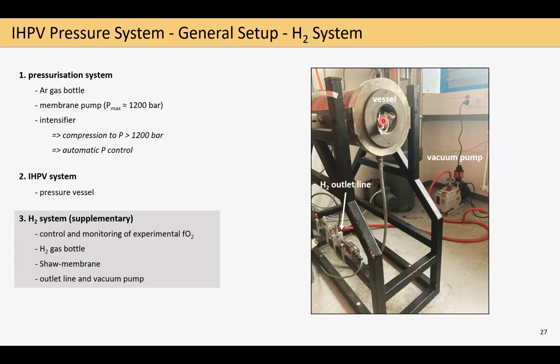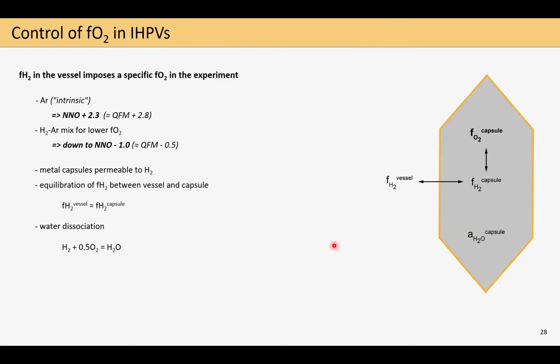So no sample holder is currently loaded here, but that would then go in here, and the Shaw membrane will be connected to this hydrogen outlet line and the pressure transducer. And speaking of fO2, let's now shortly discuss how we can control, in fact, oxygen fugacity in IHPVs. Generally, the gas which we use for pressurization, as well as the vessel, will impose a certain hydrogen fugacity in the vessel, which will result in a specific oxygen fugacity in our experiment. Meaning when we use pure argon as pressurizing gas, which we also call intrinsic in Hannover, we will get an fO2 in the experiment of around NNO+2.3, so relatively oxidizing.